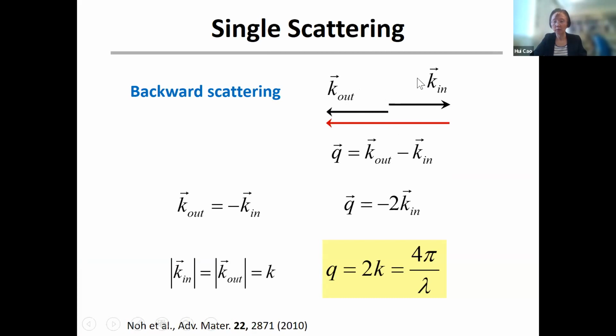The difference between k in and k out is equal to the spatial vector q of the structure. And because we consider elastic scattering, meaning k in and k out have the same amplitude, that tells us that the spatial frequency q will determine the wavelength of light that can be reflected back through this constructive interference. So that is basically what determines what we see in the backward direction. Because this dominant frequency is the same at all angles, no matter from which angle we look at this bird's feather, the color coming back to us looks the same, because the spatial frequency is the same at all angles.